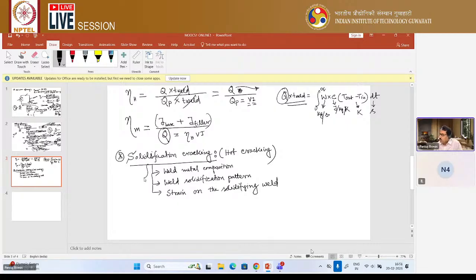Generally, if we can control these different aspects, then we can eliminate this solidification cracking phenomenon. Generally, for weld metal composition, we use a very interesting terminology called UCS. UCS stands for units of cracking susceptibility. This depends on the weld metal composition.